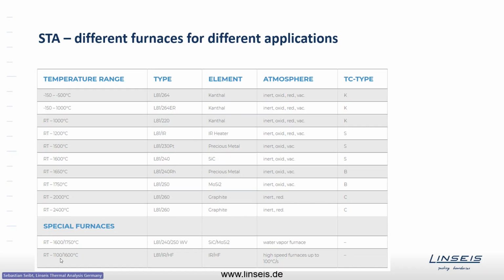We also have special furnaces. I only listed 2 of them here. We have them on demand. We have vapor furnaces. As I mentioned, we can couple water vapor units to get experiments done in humidity. And we have infrared furnaces and high-speed furnaces where you can reach very fast heating and cooling speeds up to 100°C per second. Those are available on request, for very special applications and custom designs. So that's the furnace program we offer.